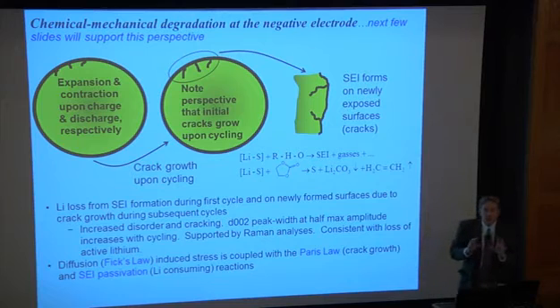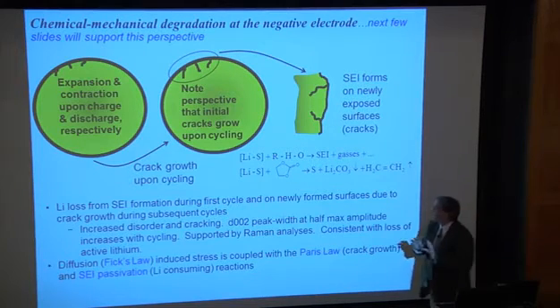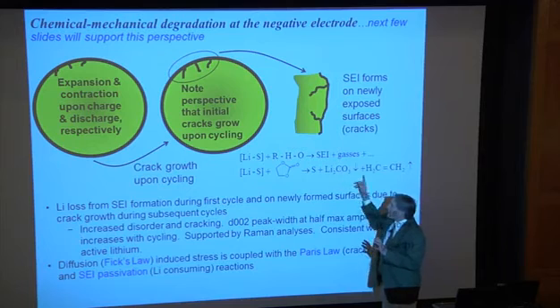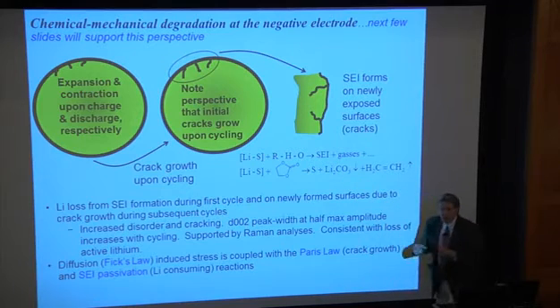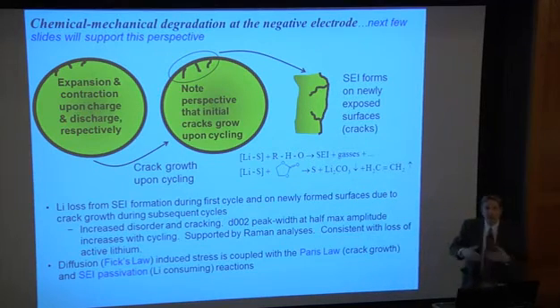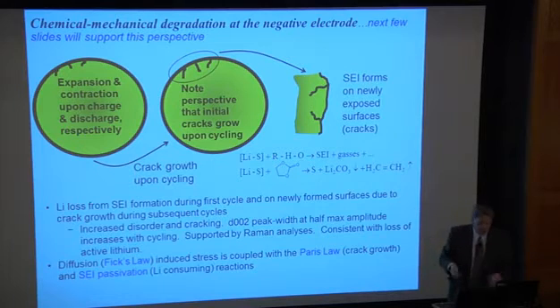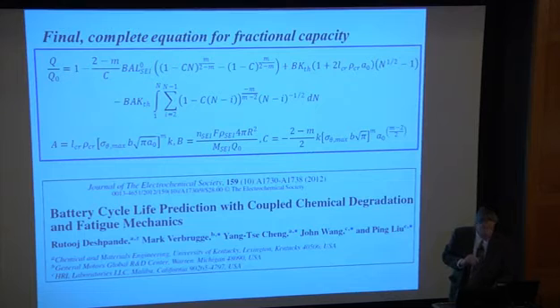And anytime you have a newly exposed crack in that carbon electrode, the negative electrode, you start to go through these passivation reactions to form new SEI, and that's lithium consuming, and that presumably is why you're getting continual lithium consumption as you cycle these batteries.